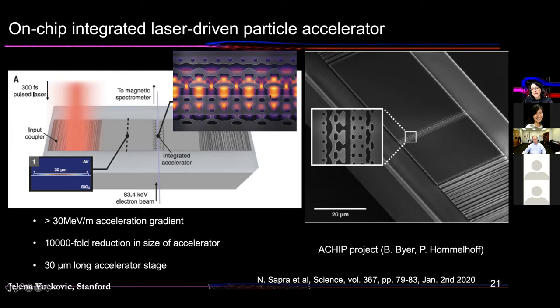And again, this is in vacuum, and this structure is made in silicon, and here we use 2 micron operating wavelength, femtosecond laser, 300 femtosecond pulse laser, which we couple to the structure. So it's not just the design of the vacuum waveguide, right? You also have to design couplers because this is a very broadband coupler for high energy laser pulses. And we also use the inverse design for that. So we couple laser pulses, guide them to the structure. And then here they couple to that particular mode that would accelerate electrons. And here is the other angled image of that stage.